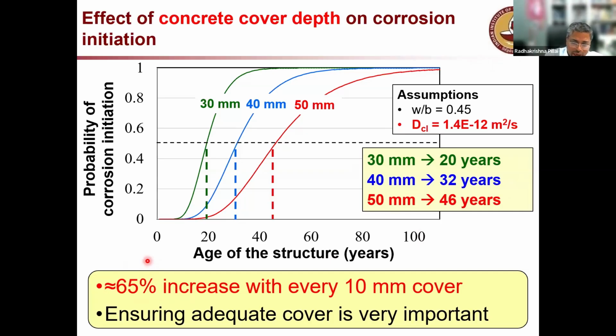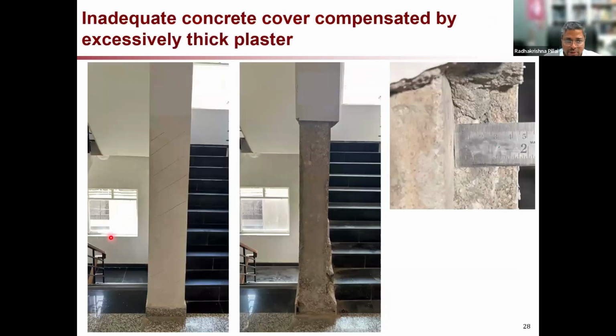Now, the point I'm trying to make is whatever is specified, make sure that it is actually achieved on the site. So here is an example where I'm showing a structure where cover was not very good. Okay, what you're seeing here is a concrete column in an apartment building. And when we removed the plaster from here, we found that the concrete on one side is good and on the other side there is very little. So in the close-up, this region is shown here, where you can see 2 inches of plaster material on one side.